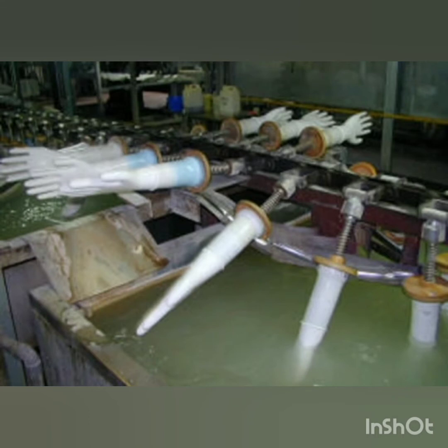A longer leaching line can wash out latex proteins more effectively. Besides that, the water must be hot and fresh enough to make the proteins dissolve better. This step is a critical step to minimize the occurrence of latex sensitivity. The water temperature, process duration, and water exchange rate will affect the effectiveness of the process. A good leaching line can result in a good and quality latex glove.